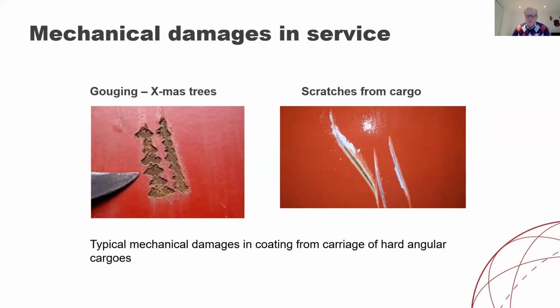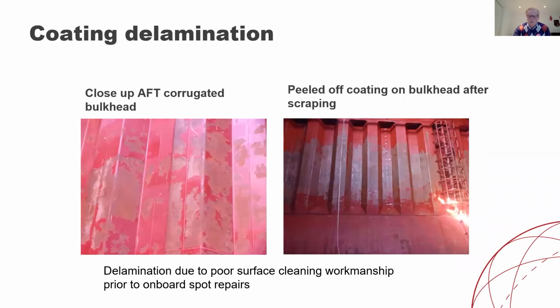Mechanical damage has already also been mentioned, when you have what you call compaction of cargoes during the voyage. You typically get these gouging damages, or what we call Christmas tree damages. When you load or offload, you can get these scratches to the cargo hold coating, and particularly these hard angular cargoes make this type of damage. Coating delamination. This is delamination due to poor surface cleaning and workmanship prior to onboard spot repairs, and then you will have peeled off coatings, scraping here, as you can see.